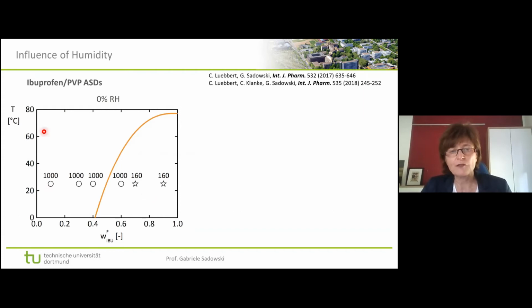Before that, I show you the results of our formulation storage measurements. At this time, this is not months, but days, obviously. And again, we found crystals here after 160 days. We have no crystals so far after more than 3 years.